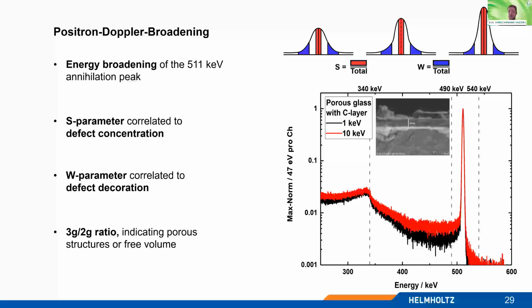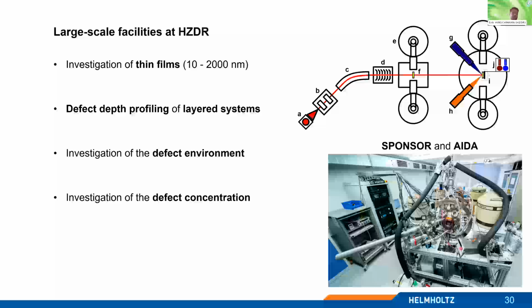The third parameter you can see here is the so-called 3 gamma to 2 gamma ratio, which is placed in the middle of this energy spectrum. This is an indicator for porous structure, or an increase or decrease of pores in your system. What you can't do with this machine is measure the positron lifetime. But nevertheless, same procedure: you can investigate thin films with this machine up to 2000 nanometer.